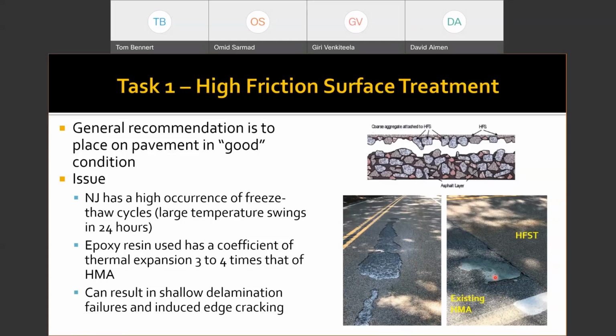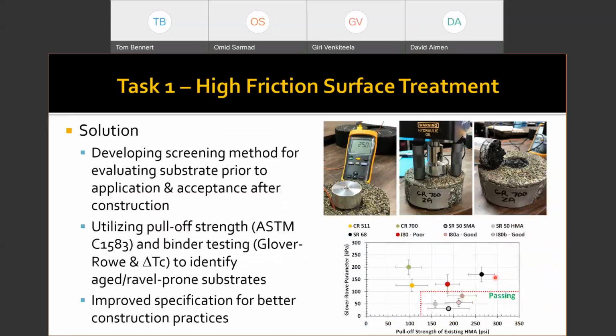So we looked at a number of different pavement sections that had HFST on them, both good and poor performing, and what we were able to do in this study was two things. The first one was to design a pre-screening protocol that can be used to determine whether asphalt pavement sections are good candidates for HFST, for epoxy resin HFST. You can see down here, we look at a property from the asphalt binder, so we have to recover some of the asphalt binder from the surface of the pavement. And then we also look at what we call the pull-off strength. That's shown in the pictures above, where we're running a pull-off strength test to determine how strong the HFST bond is onto the pavement. So we can run this series of tests to pre-screen the asphalt pavement prior to application to make sure that these distresses don't occur.